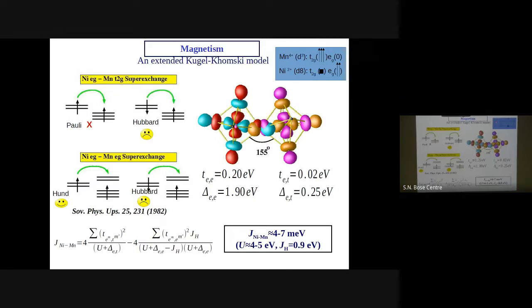As it so happens, of course, this is La2MnNiO6. Lanthanum is 3+, oxygen is a 2- anion. So together, manganese and nickel can be both 3+, or one can be 3+ and the other 4+. Both are possible. Manganese here happens to be in 4+. The calculation shows that, and the measurement shows that. And nickel is in 2+. So in an octahedral environment, there will be splitting of the d level into t2g and eg. In the case of manganese 4+, d3, I have t2g where there are 3 up-spin electrons and eg is empty. For nickel 2+, d8, t2g is dead because it's completely filled, and the eg is half-filled. So that is the situation.